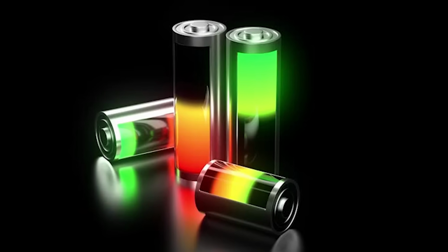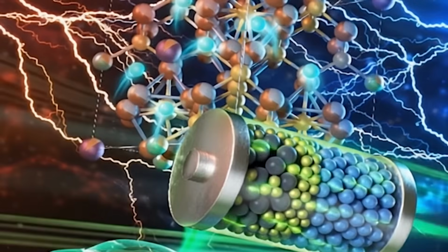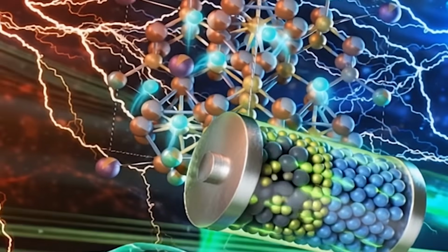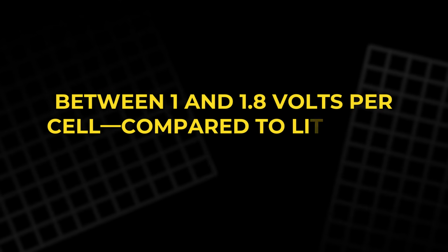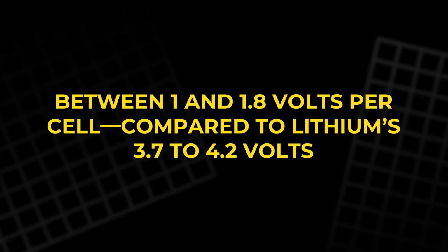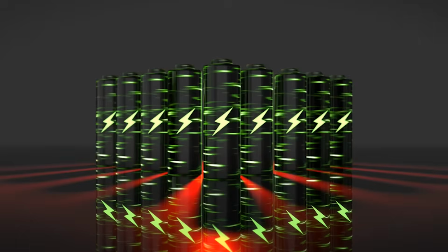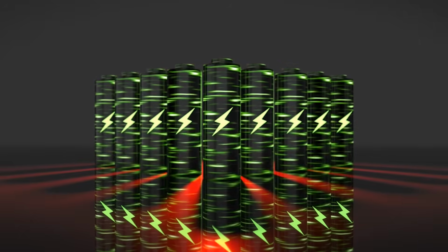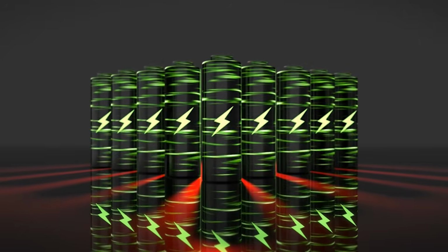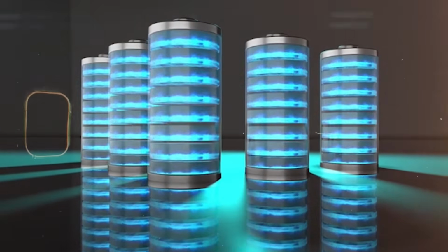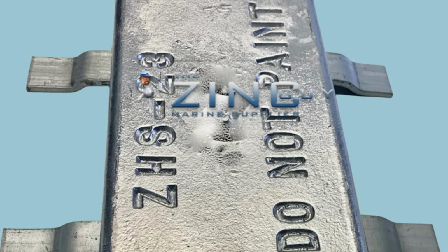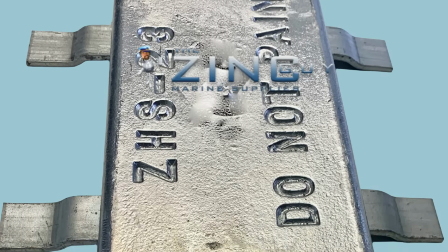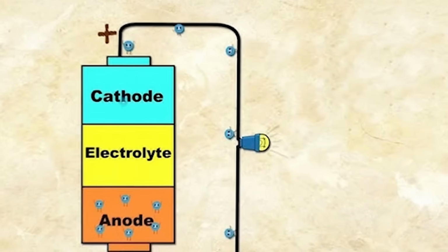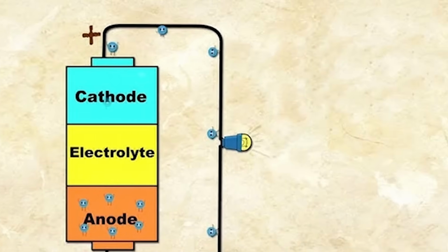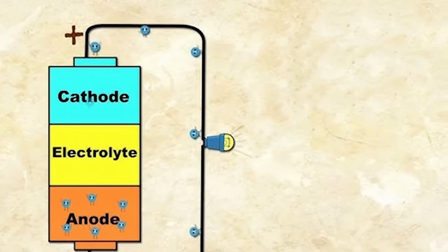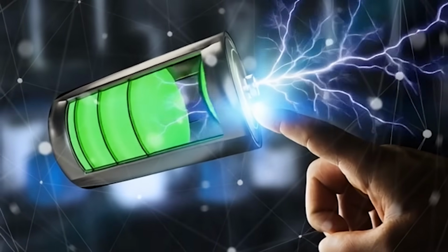Still, no technology is without flaws. The Zinc NZVO system operates at lower voltages, between 1 and 1.8 volts per cell, compared to lithium's 3.7 to 4.2 volts. This means more cells must be connected in series to achieve the same total voltage, increasing complexity in battery management systems. There is also the persistent challenge of dendrite formation on the zinc anode. Though researchers have proposed various coatings and electrolyte additives to suppress it, long-term behavior at scale remains uncertain.